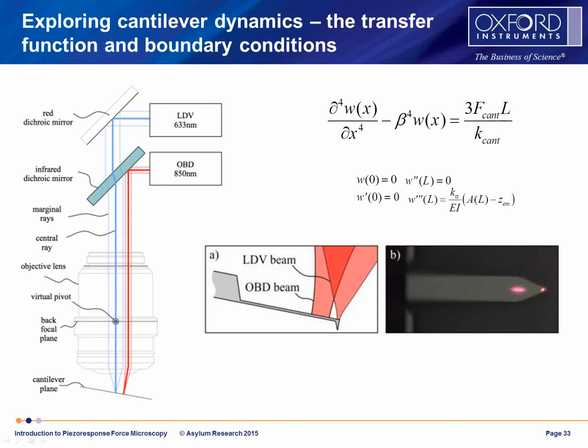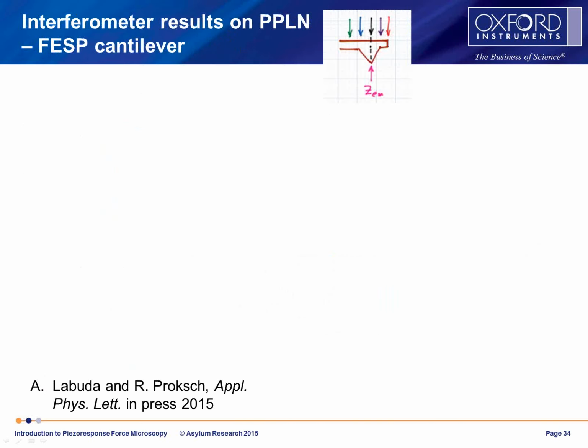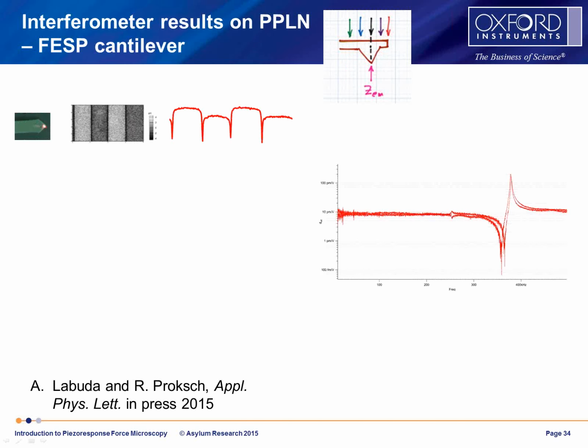different positions. And in fact, based on my earlier discussion, we can start to look at the boundary conditions by positioning that spot at the boundaries. So the following is showing you trying to probe this boundary condition. And again, we're on PPLN. The cantilever that we used in this case has a shape a little bit like this from the side, where the tip, you can't actually see it from the top. So what we've done is we've positioned the spot at the very tip and measured domains in the PPLN.